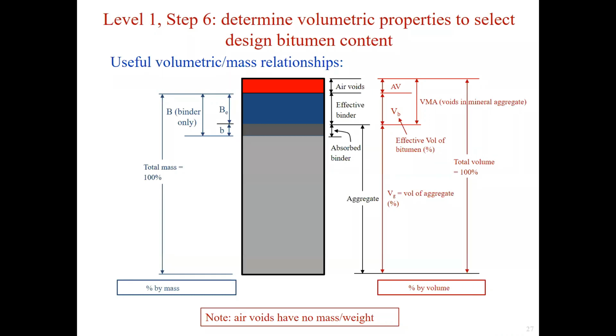If the relationship is expressed in terms of mass or volume, here's how the composition looks. If we look at mass, normally the air voids have no weight. The binder is expressed as capital B, BE stands for the effective binder, and small b for absorbed binder.